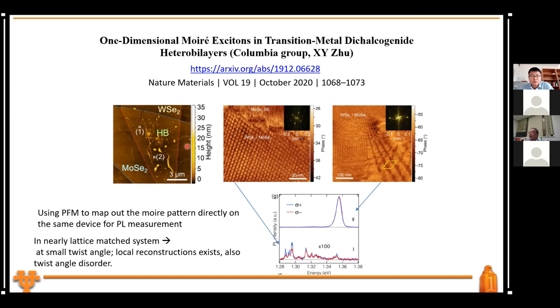this. This was also the time when I visited Columbia to give my talk, and Ape showed me. I said, well, there's no direct confirmation from any of these optical measurements of the structure of the moiré pattern. And he pulled out this paper and showed it to me. He said, Ken, let me show you, we seem to have seen this, right? Not everything can be done in UHV STM, right? But with this one you can just use piezo force microscopy, and measure it when the sample is on an insulator, because when you do optical spectroscopy, the sample needs to be fabricated on an insulator.